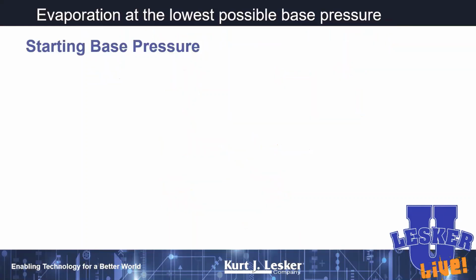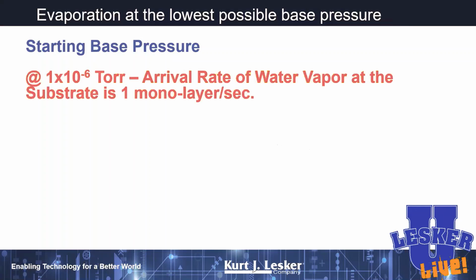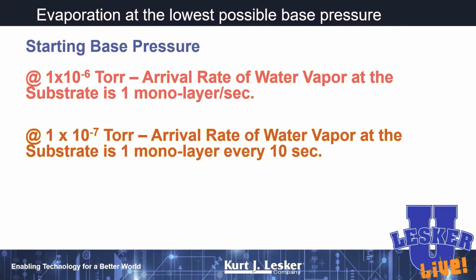Now on base pressures, let me just mention, let's talk about mean free path a little bit. If we talk about getting into high vacuum, 10 to the minus 6 torr, just keep in mind that even at that low pressure, you're depositing a monolayer of water on your thin film substrates every second. That's how much water is in your vacuum systems. If we go down a decade in pressure, we can extend that time to form that monolayer up to maybe 10 seconds. And keep in mind, a monolayer of water is 10 to the power 15 molecules per square centimeter.